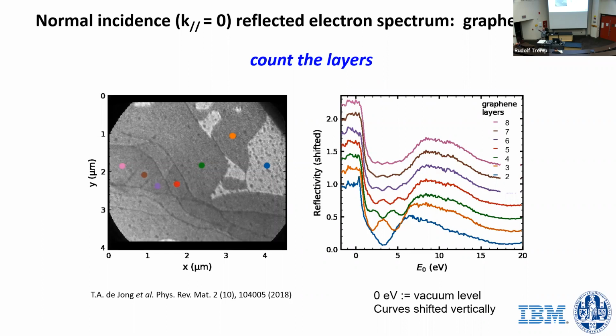If I have two layers of graphene, we can have a state that lives just between those two layers. And this minimum occurs just at the energy of that state. So now we have a state, the electrons can go in there. And so the reflectivity is very small. If I add a layer, then I have a state between the first layer and the second layer and the third layer. They interact with each other and they split, right? They lift the degeneracy. So now I get two of these minima, etc. So you can count how many layers you have from this.